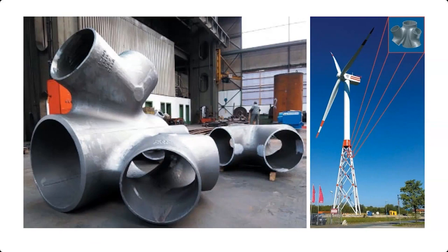You can see in the inset on the right there that this is an onshore mock-up of what will be an offshore wind turbine. And so at that red location there is where this joint lives. If there are any architects on the line, this is a beautiful looking thing, but it will spend its entire lifetime underwater. So it's not only in architecturally exposed applications where we can think of castings, they're actually very hard working. And that's why I start with this example to preclude this sort of myth that castings are brittle and that they crack and that they have poor material qualities. A properly designed and properly specified casting will have isotropic materials and can outperform, material-wise, wrought steel.